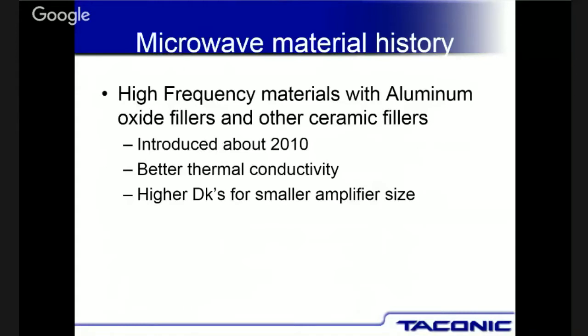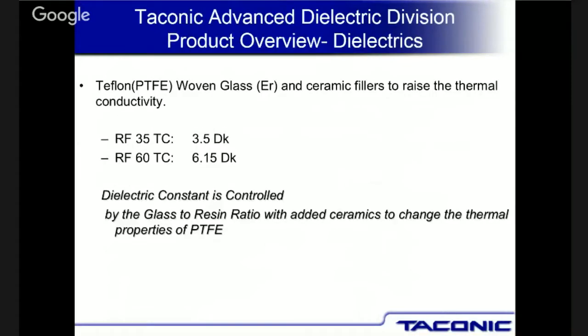And so actually, it's probably only been a couple years now, I'm thinking, well, 2010 I have on here. We started looking at other fillers that we could stick in the material, like take a little bit of ceramics out and put some aluminum oxide in the material. And so we now have some materials which, and this is not just us, but our industry, people are using aluminum oxide, and that changes the thermal conductivity without drastically changing the electrical properties of the material. And so now this is the one that you guys are starting to use.